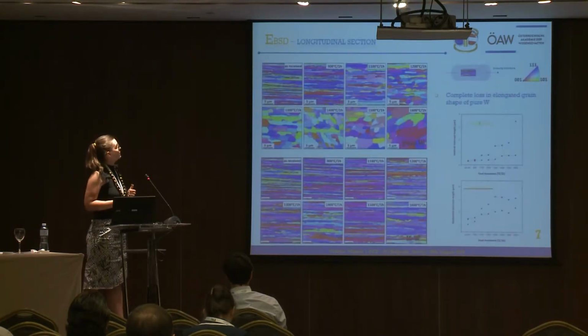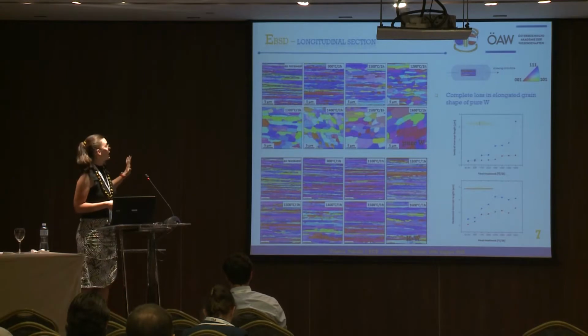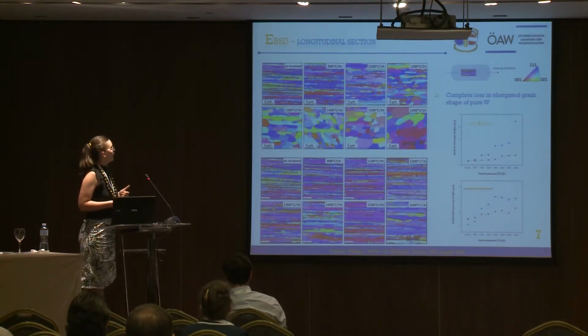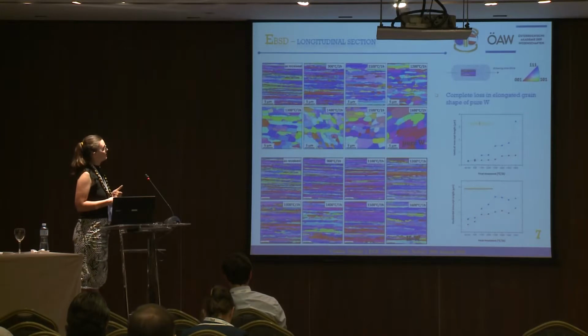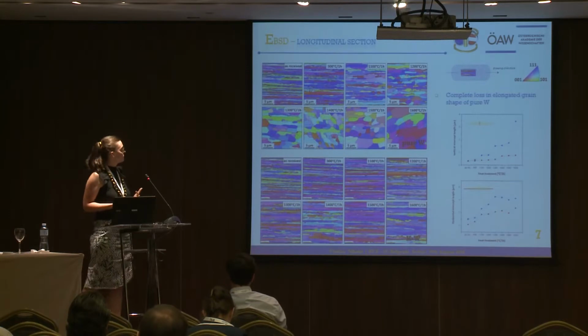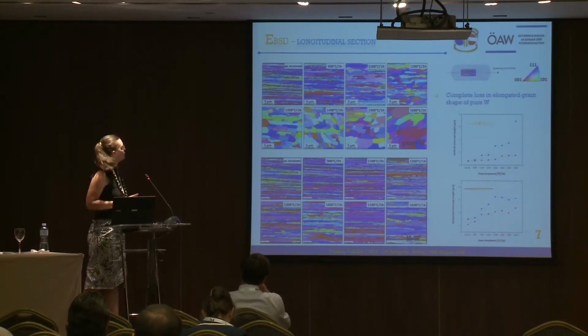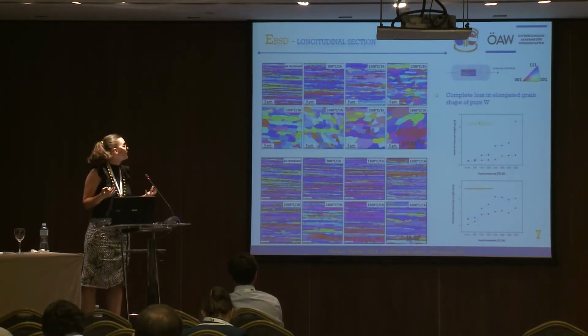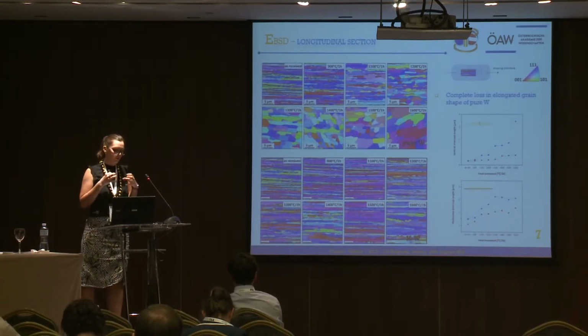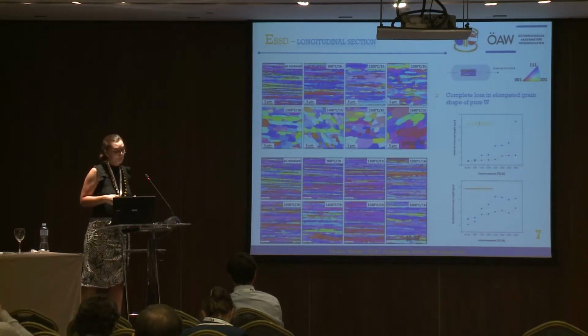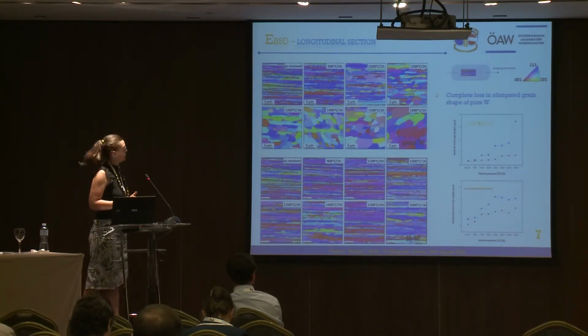And now let's look at the longitudinal section, so from the side of the wire. Here we can see these elongated grains again, and again the same comparison is done. For the pure tungsten, already at an intermediate temperature range, we can see quite extensive changes in the grain morphology, and upon the highest annealing treatment, there is a complete loss of the elongated grain structure. They change to round, quite globular, large grains. In contrast to that, the potassium doped one is again quite stable.